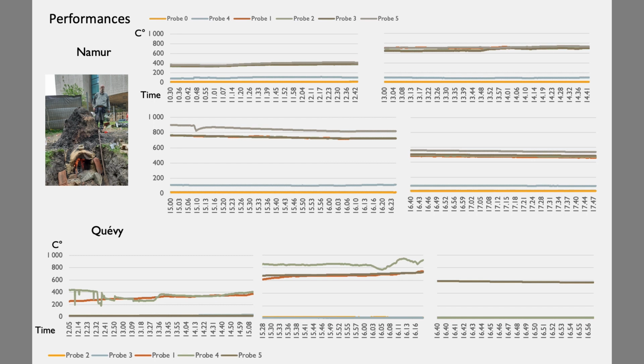For the kiln from Quévy, it was, on the contrary, very difficult to raise the temperatures. Maintaining and homogenizing them was also very complicated. Still, after 5 hours of hard work, 800 degrees were reached. The kiln was then closed and covered with branches coated with slip. It was closed with a metal plate. Nearly half of a stere of wood was burned during these 5 hours.